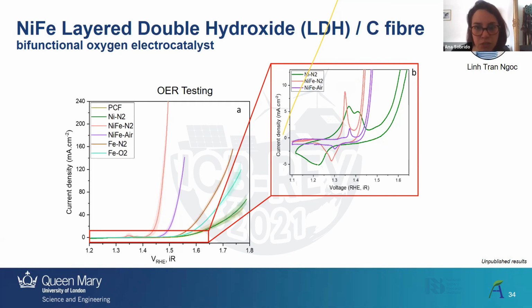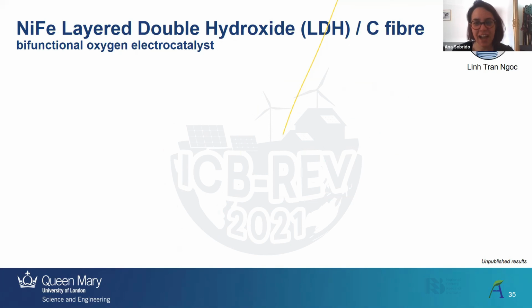redox reactions. And in green, we have our standard, which is just the nickel without iron, and then we have the nickel iron prepared under flowing nitrogen and the nickel iron prepared under static air. And then you can see how different those peaks are, and how quite shifted they are, especially versus just the nickel as well. Knowing that this corresponds to the nickel oxidation, that's quite intriguing as well. We still don't have an answer for that. So we're still working on trying to understand what's going on.